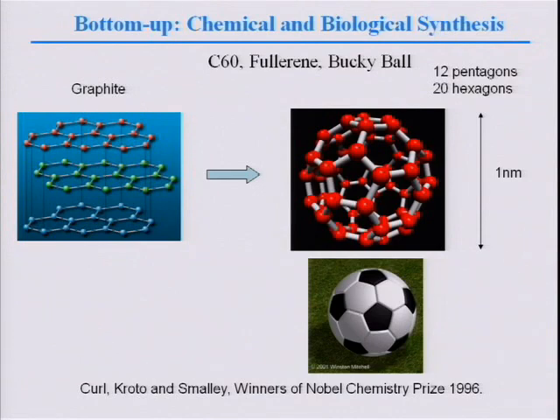One example is carbon-60. Carbon-60 was discovered by these three people. They are the winners of the Nobel Chemistry Prize in 1996. Taking a graphite structure, graphite has a layer-by-layer crystal structure. If you use a laser to evaporate graphite with certain catalysts around, you can produce this beautiful ball, about 1 nanometer in size, which people call a Bucky ball. It has 12 pentagons and 20 hexagons, exactly like a soccer ball. This Bucky ball has a structure beautiful enough to get these people awarded a Nobel Prize.